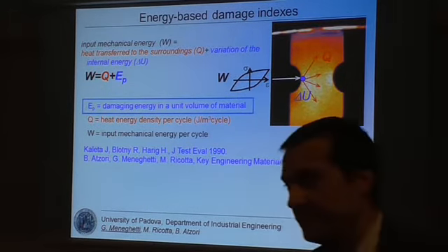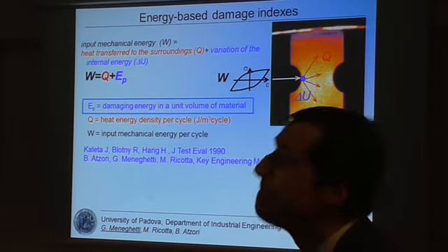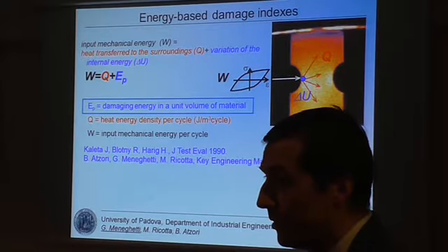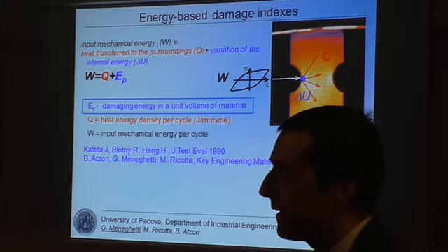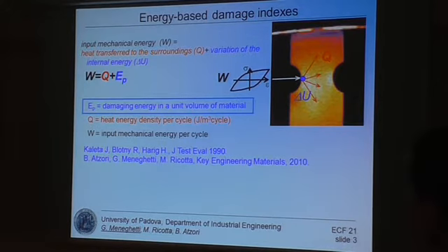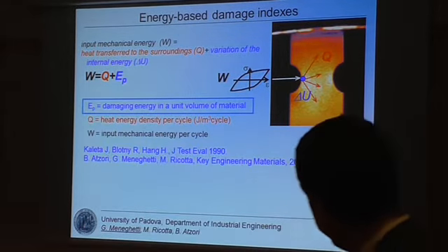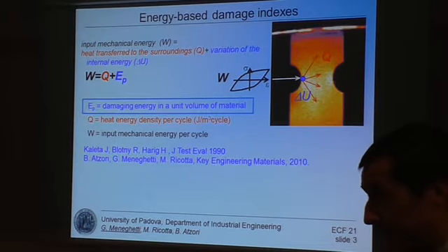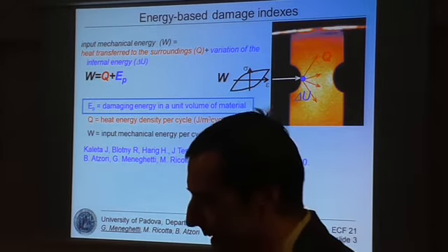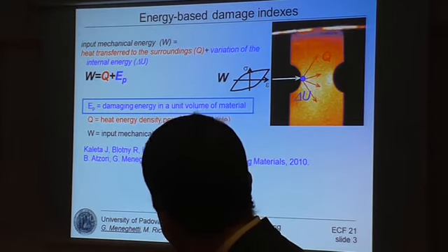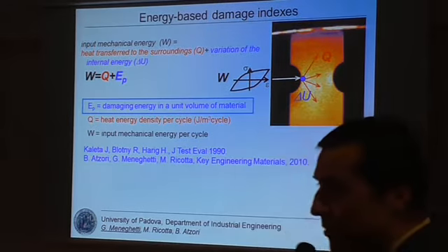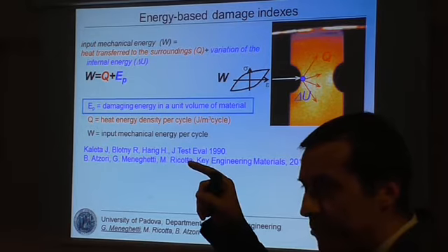You have shown some results under mostly uniaxial loading, and when I turn to other kinds of loading, to pure shear loading, what happens? Okay. We did, not in this paper, only a few experimental tests in pure torsion loading, and what we found in a different material, not this one, a room temperature ductile iron in that case, is that in very high cycle fatigue, the energy fatigue curves between uniaxial and pure shear tend to coincide. Not the same in low cycle fatigue.